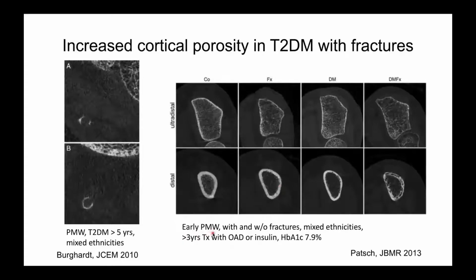Here it was early postmenopausal women with and without fractures, mixed ethnicities, at least 3 years of treatment with a diabetic drug. And here I point out the HbA1c was about 8%. I'll come back to that notion. And what she showed again was that there was more porosity in diabetic bones, but particularly in those who had fractures, perhaps suggesting that this porosity in diabetics might be related to greater propensity to fractures.